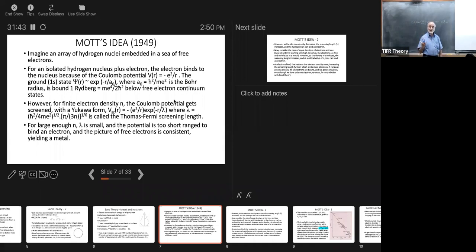What he found was that if you have a semiconductor and you dope it with some amount of impurities, these impurities typically, as I'll show you later, create hydrogenic states. Basically, they are fat hydrogen atoms that are anywhere from 10 angstroms to 500 angstroms in size. But their basic physics is that of the hydrogen atom. So it's 1 electron per hydrogen atom. And what was found experimentally was that when you dope it very lightly, if you don't put too many of these dopants, the semiconductor remains a semiconductor. It did not become metallic. Whereas band theory would say immediately that you have 1 electron per site, and therefore it should become metallic because it's only a half-filled band.